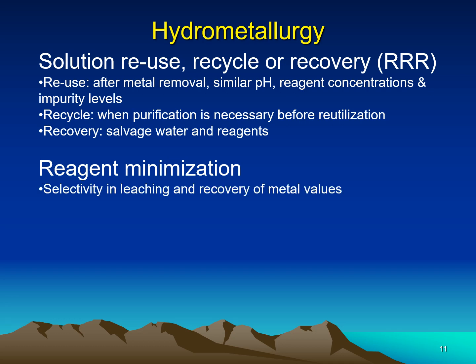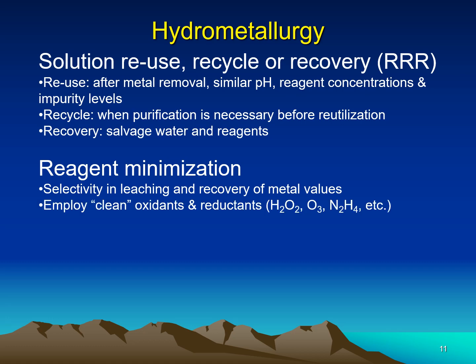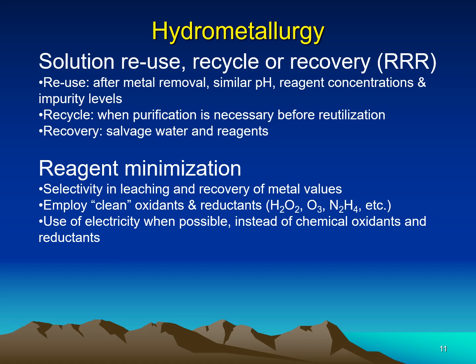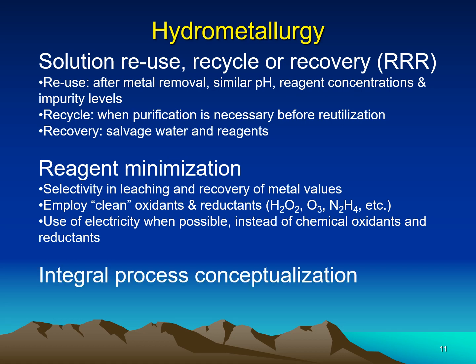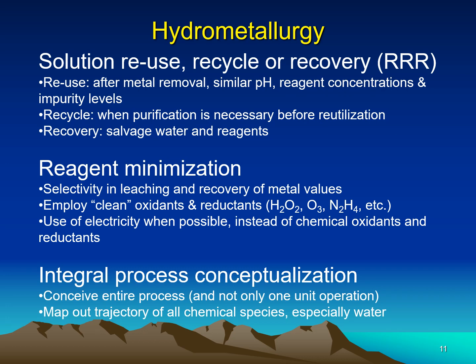Reagent minimization: selectivity in leaching and recovery of metal values. Employ clean oxidants and reductants such as peroxide, ozone, and hydrazine, among others. Use of electricity when possible instead of chemical oxidants and reductants. Integral process conceptualization. This is to try to conceive the entire process and not only one unit operation, not only leaching or solvent extraction, the entire process. And map out the trajectory of all the chemical species, especially water.